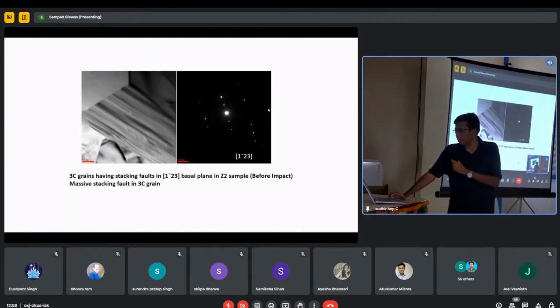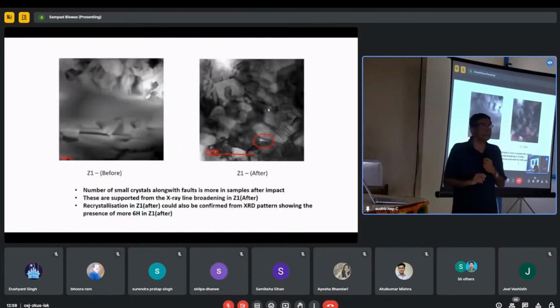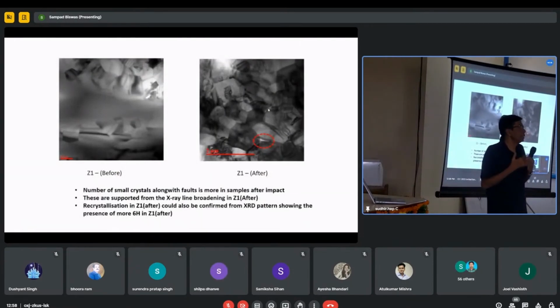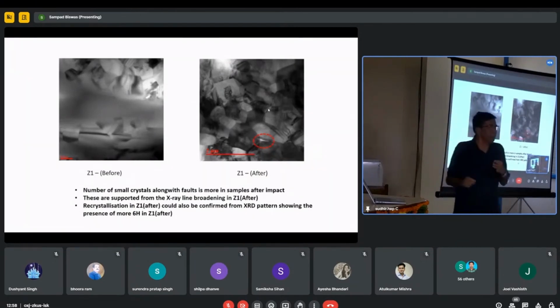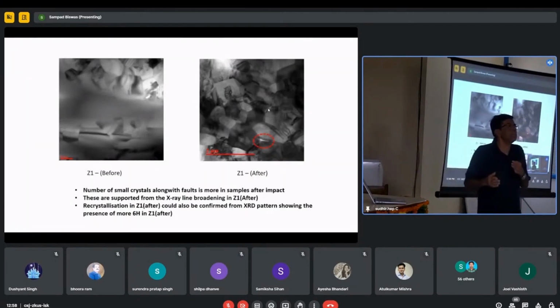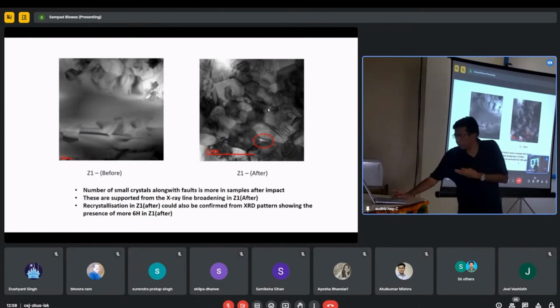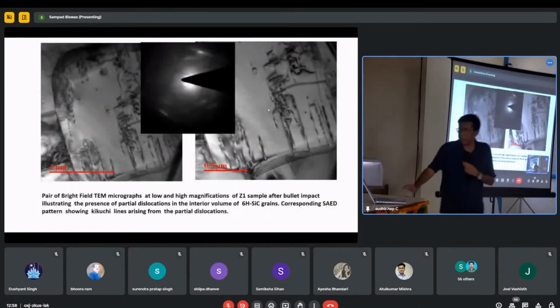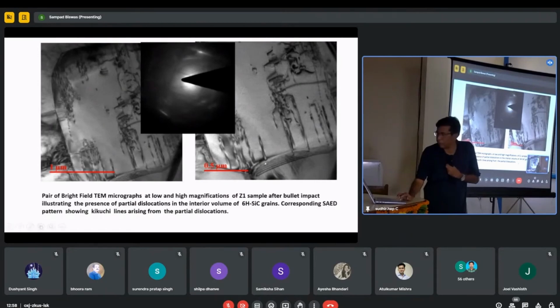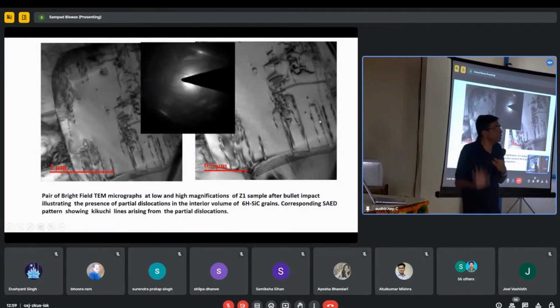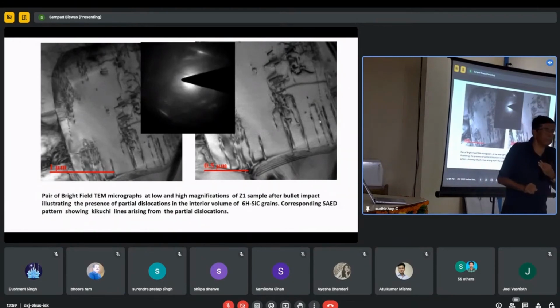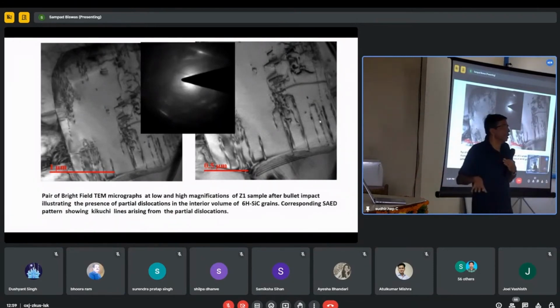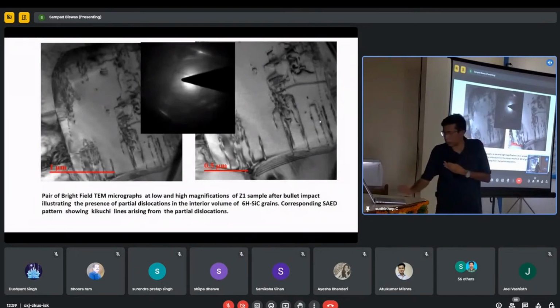This is a 3C variety. I'm not going into details of it. What we wanted to say is that a lot of dislocation activities were there during the shock process, while these were in the plasticity region, and these dislocations create defects which you can find later. I am showing you. See, if you look at it, a typical Shockley defect: you can find one dislocation creating the defect here, the other dislocation creating another stacking fault here, a third dislocation creating the third stacking fault here. This is a typical Shockley defect created by the dislocation and by the shear stresses applied to this material during the shocking.